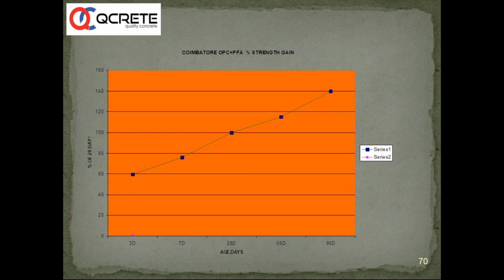We did this in Coimbatore, and you can see a 40% jump between 28 days to 90 days. So this is a huge benefit to the customer actually. So a customer buying concrete can have 20 to 40% jump between 28 days to 90 days.